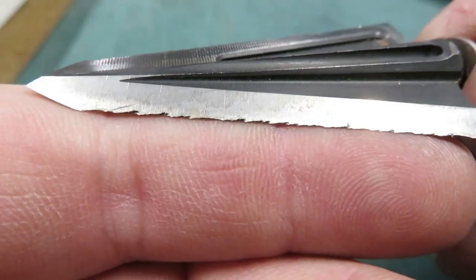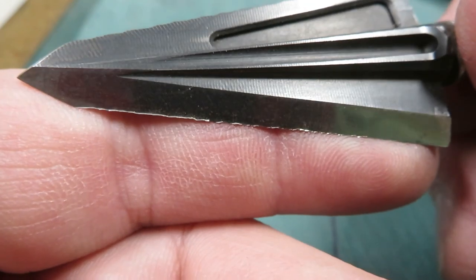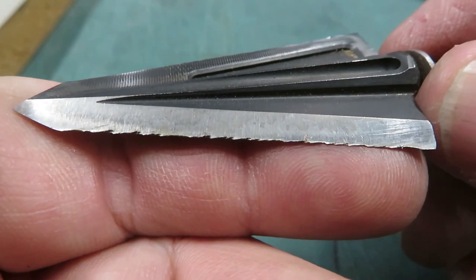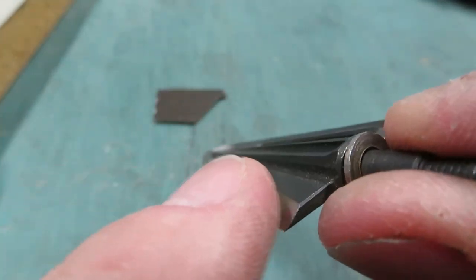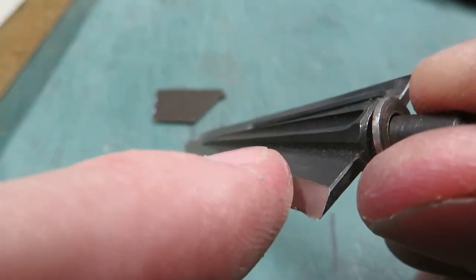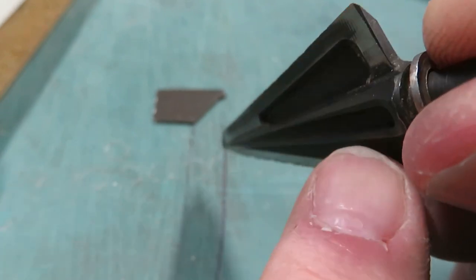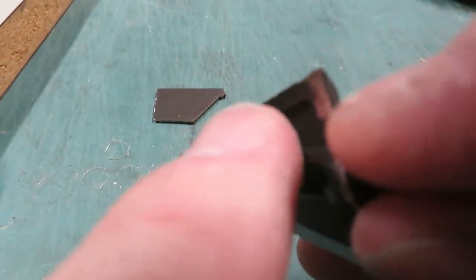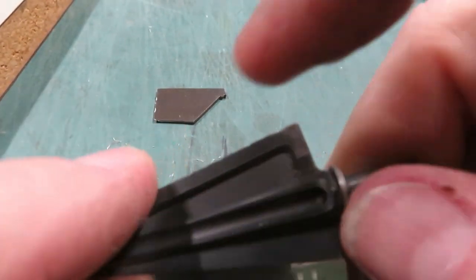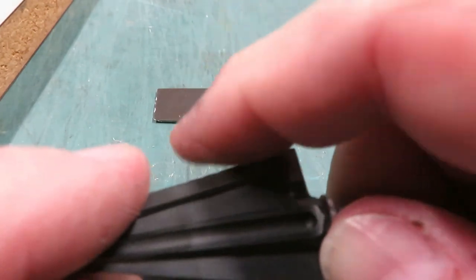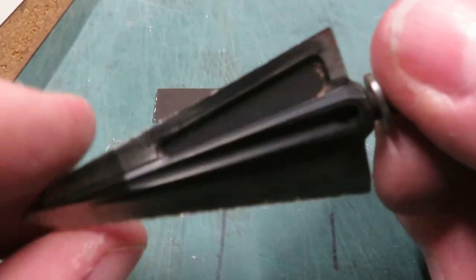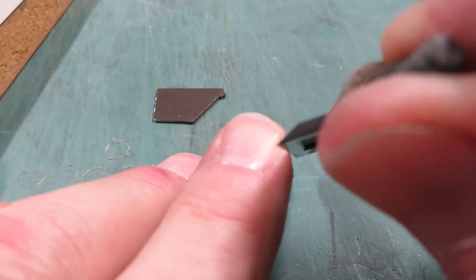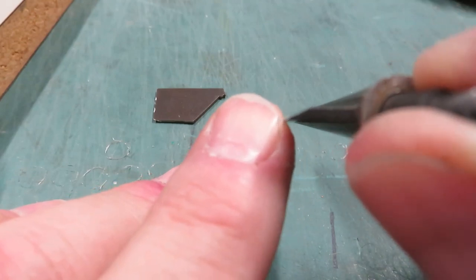I'm going to show you this under a microscope and explain edge rolling and edge breaking. That will make a little bit more sense under magnification. You can see it pretty well here, but there has to be some metal behind a single bevel. Yes, you get more rotation with a longer bevel—it's got more forces to push on this side and that side—but during that rotation there is side loading taking place. Can that edge withstand it? That is a product of material being there, more than the recipe in the metal.